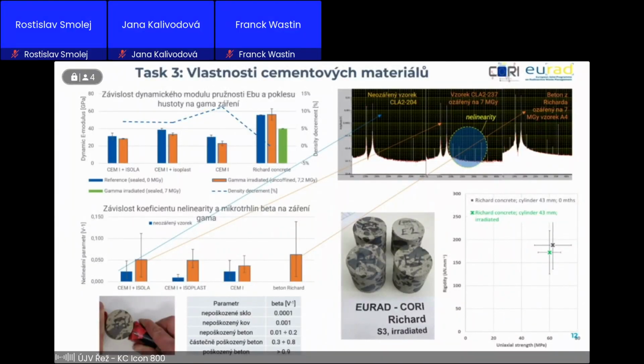In the samples with plastificators, there was some decrement of the moisture during irradiation, of course, because it was not covered by anything. It was simple. And in the case where there was no plastificator, the sample lost a lot of water. Also, on the right-hand side, when we did the rigidity test on the Ricard concrete, there was a small decrement of the rigidity after irradiation, which is also shown in the green column.